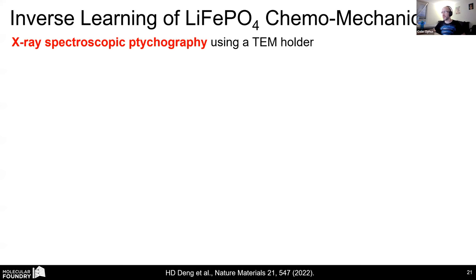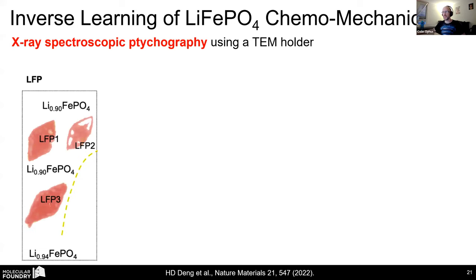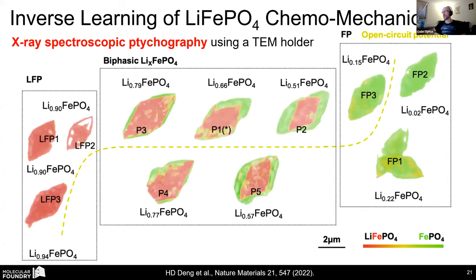So another example, this one is from Will Chueh's group, a collaboration at Stanford, actually. They take these lithium iron phosphate particles and they do synchrotron studies as they delithiate the material here, as they change the potential voltage across these grains. So these are primary cathode particles of lithium iron phosphate, colored by the different amounts of lithium. And this is done at the COSMIC beamline at Berkeley Lab. It uses a TEM sample holder.